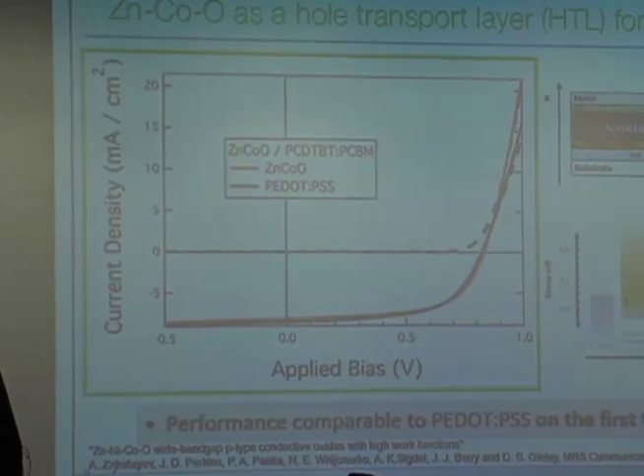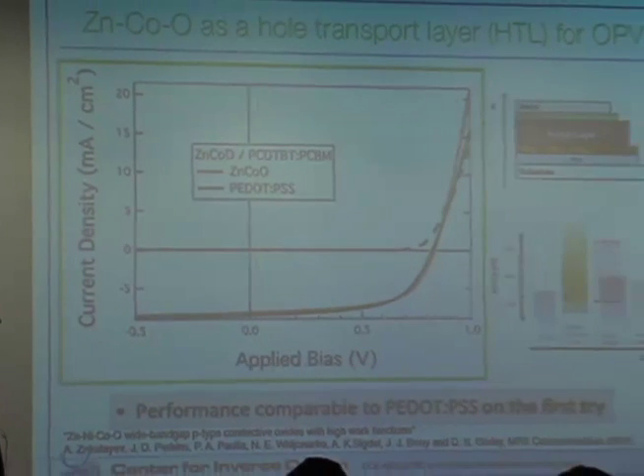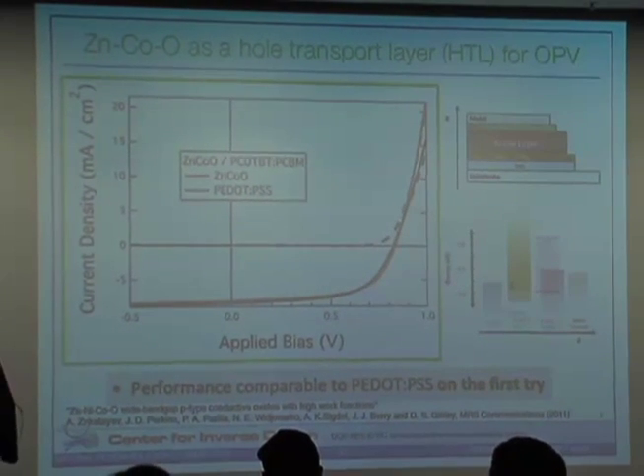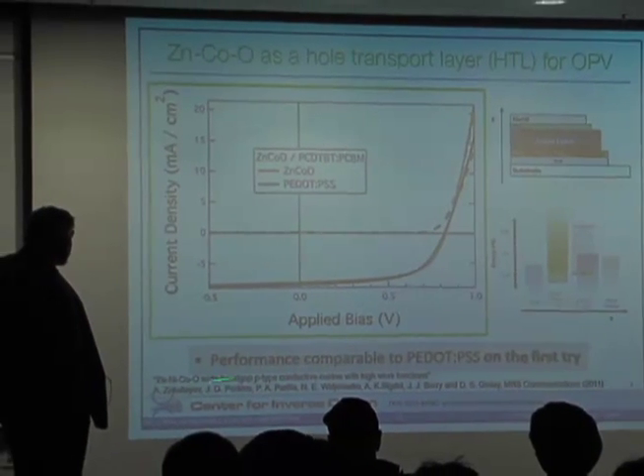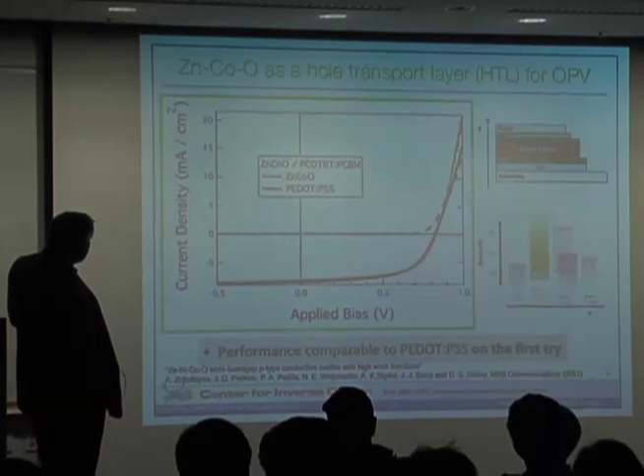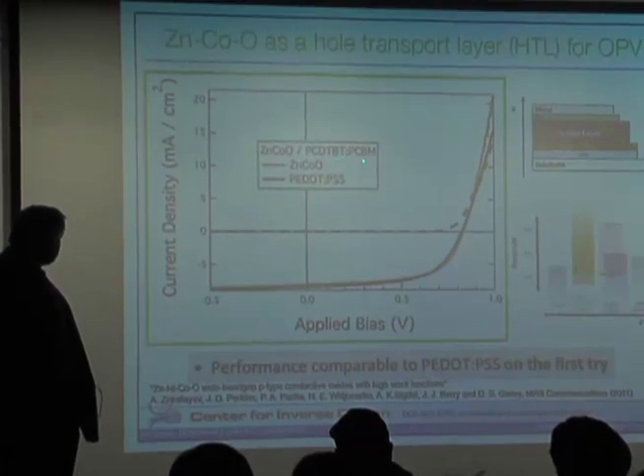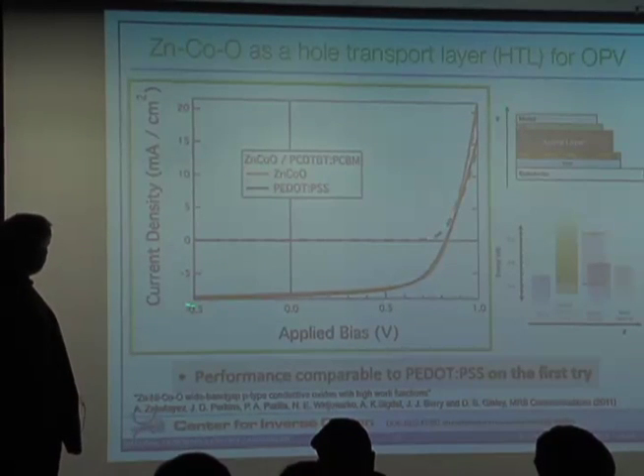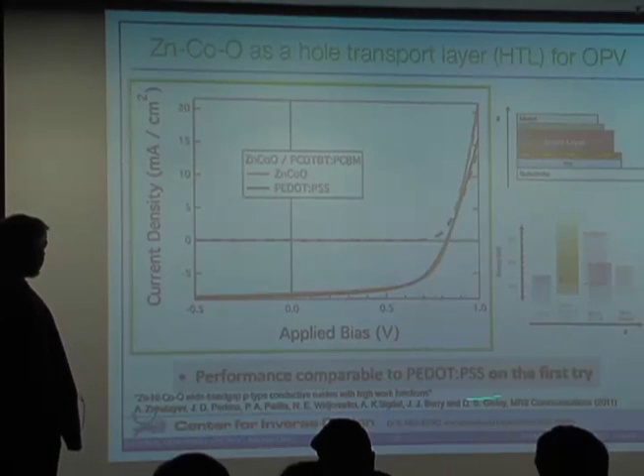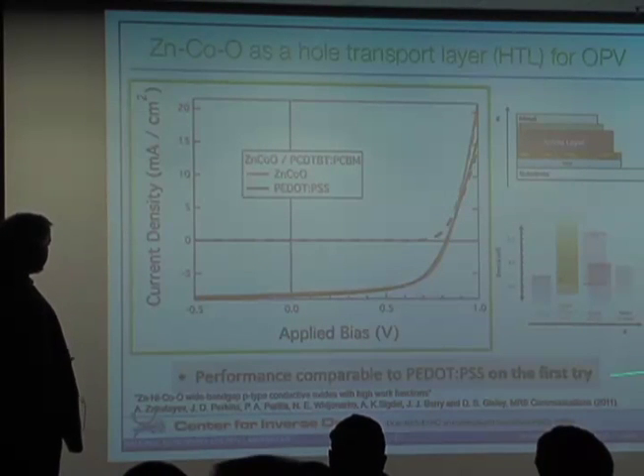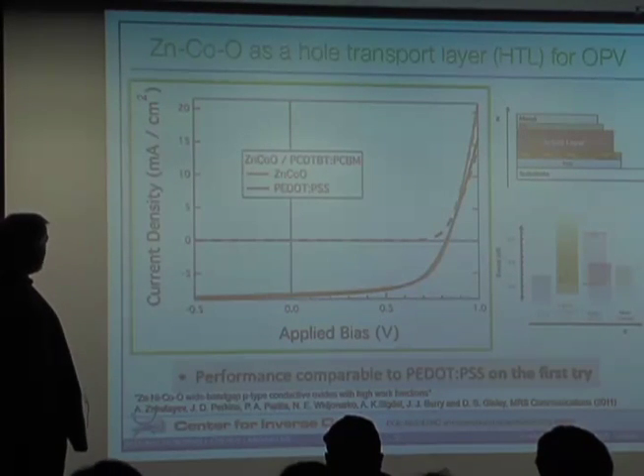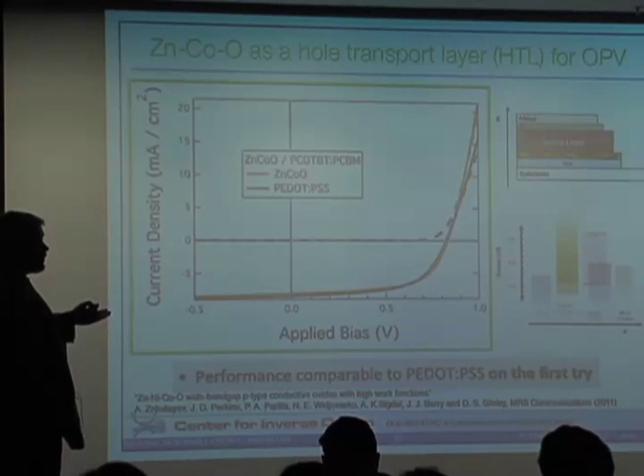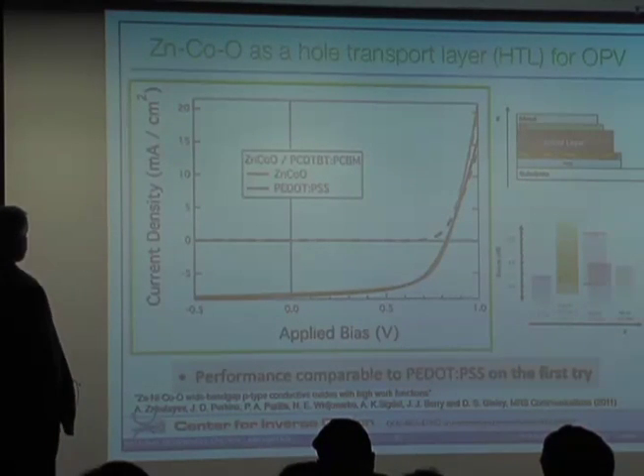And so with the EFRC out of Arizona State, which has been looking at interfaces for organic photovoltaic devices, we had a nice collaborative publication where we showed we could use this zinc cobalt oxide system as a hole transport layer. This is the profile of it. And in fact, the performance is pretty comparable to PEDOT:PSS without any real optimization. So even if we can't get all of the functionality, say transport and hole concentrations, we can get some of that functionality for other applications like hole transport layers.